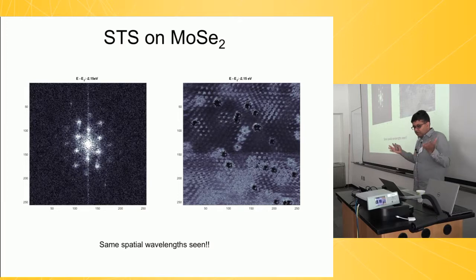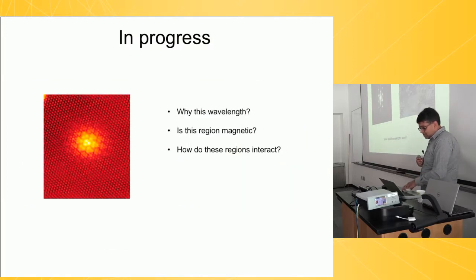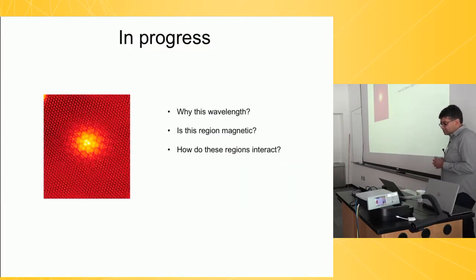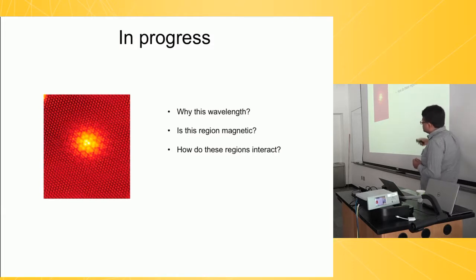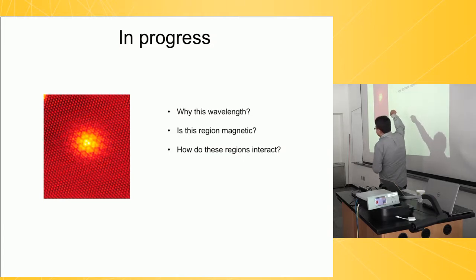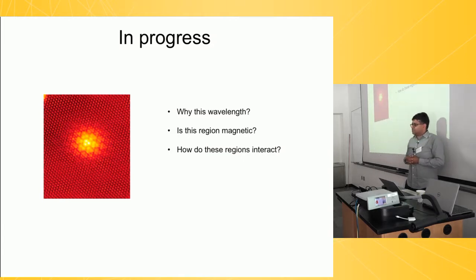As of now, we don't really know why this thing exists. So in progress, we need to understand why there is this wavelength. Second, once you have such a wavelength, is it possible that this entire region of the sample is magnetic? If you imagine, for example, that this is associated with lattice distortions, the lattice distortion can locally change the charge state of the molybdenum, which can certainly give rise to magnetism, for example.